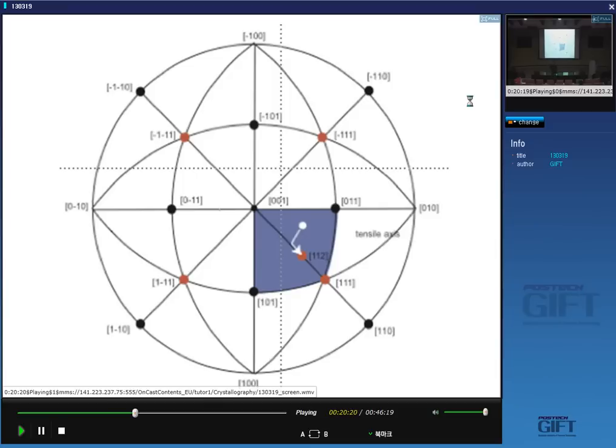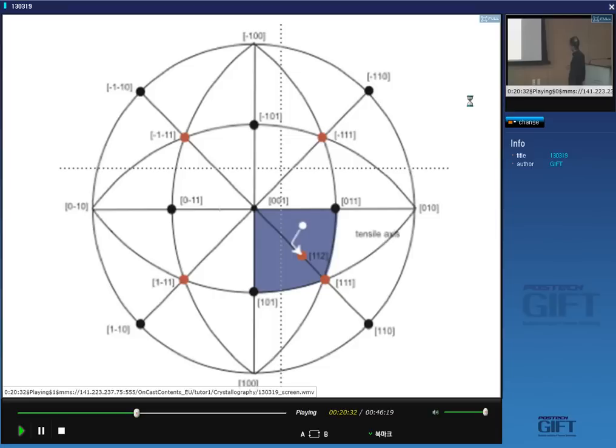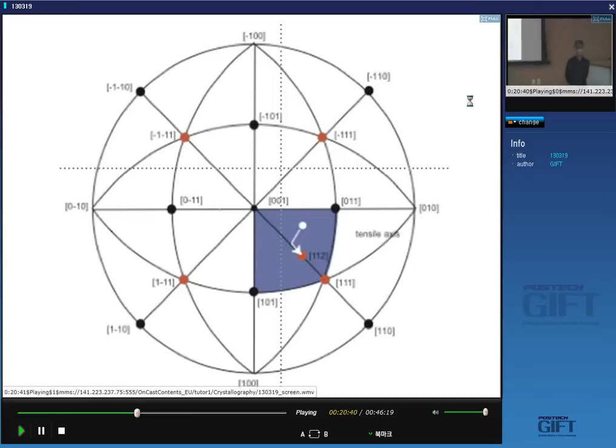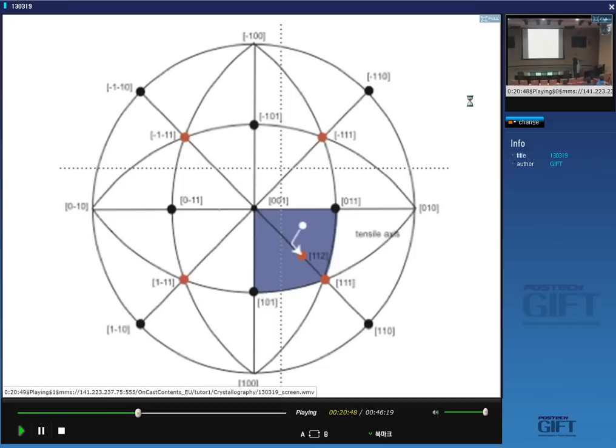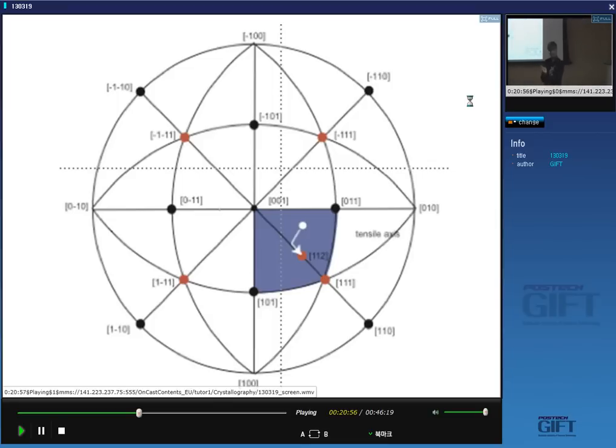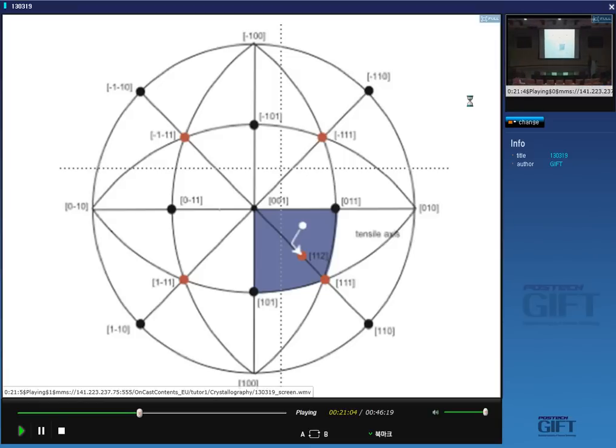Once on this boundary edge between two triangles, the arrow moves towards a [112] direction because the tensile axis must move towards the average of the two slip directions. For example, one slip direction plus the other slip direction sum to give a [112]. So the tensile axis is moving towards the average of the two slip directions.